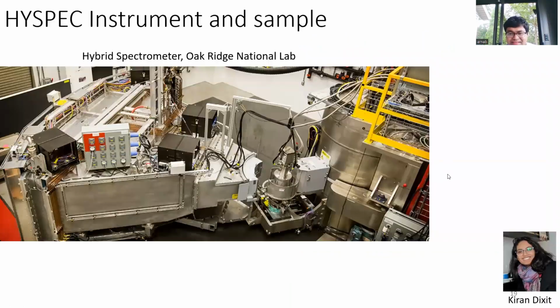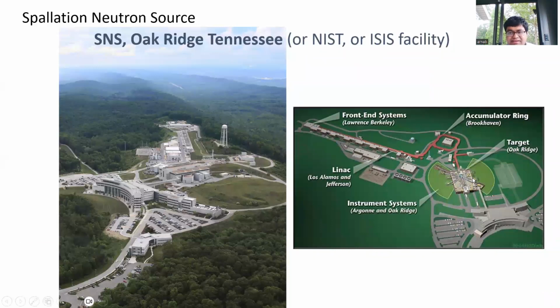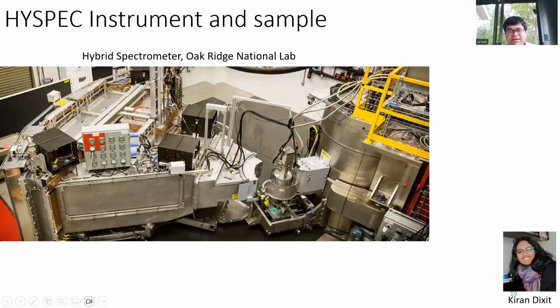And at the end, one of these end stations that you see here, in fact, this one right here that I'm showing, is basically this humongous giant thing, the HYSPEC or the hybrid spectrometer at Oak Ridge National Lab. This is how it looks. This is where the sample sits. You can fit a dilution refrigerator here, or a very strong magnet here. And your sample goes right into this spot. There are polarizing optics here, polarizing optics there. And this whole drum that you see can move. This is the 2 theta arm. These are on air pads and can move on this floor. And so that's how you move and do these measurements.